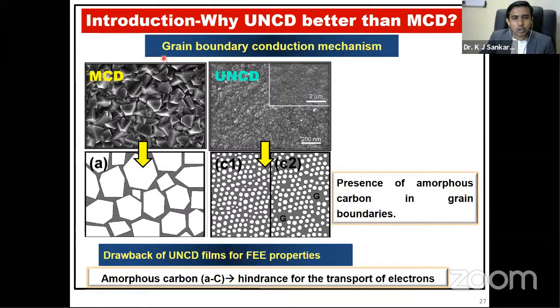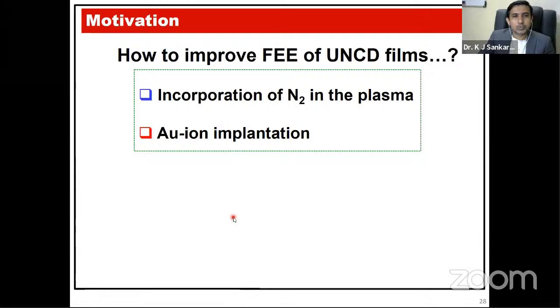But there is also a drawback for the UNCD, because the amorphous carbon in the grain boundaries is also not conducting enough. That amorphous carbon hinders the transport of the electrons in the UNCD films. So how can we make the UNCD films highly conducting? We would like to improve the field electron emission of UNCD films by two methods. One is the incorporation of nitrogen in the plasma, because these UNCD films were grown in methane and argon plasma. And another method is gold ion implantation. So first I'll start with the incorporation of nitrogen in the plasma.